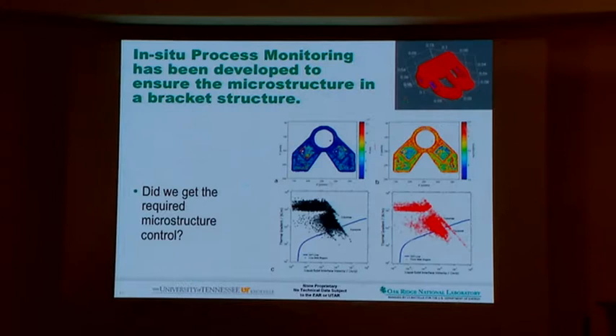So this is what we are building. It's a complicated structure. It's just a small bracket. And you can see that the square area is where we implemented this rapid firing spot melt pattern, which creates a low thermal gradient. And everywhere else, we used the same stationary, like raster path for melting. And then we did move from columnar to equiaxed.